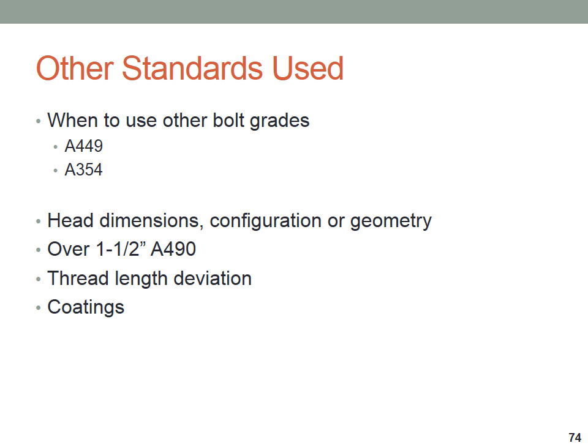449 and 354 are referenced within our structural bolt specification. Some examples of that are if, for whatever design reason, you need a countersunk head. If you have thick plies that need to be pulled together and you don't think the standard thread length might be enough. If you need larger than 1.5 inch diameter. If you need a coating that is not specifically permitted by A325 or A490. These are good opportunities to use 449 and 354.